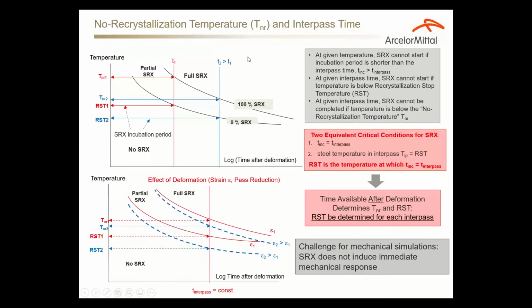Another recrystallization control is related to partial to static recrystallization, and this is much more challenging because, first of all, static recrystallization does not produce immediate mechanical response, so we cannot directly use mechanical tests to assess static recrystallization. And time after deformation is one additional parameter that affects all the kinetics and the onset of static recrystallization.